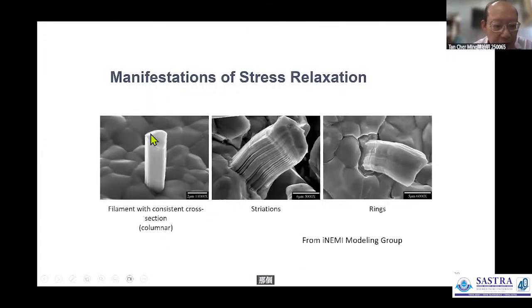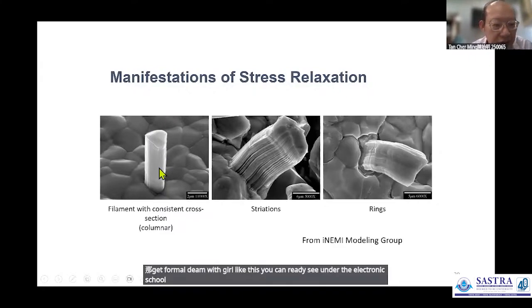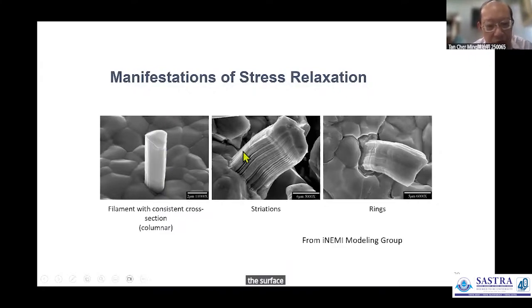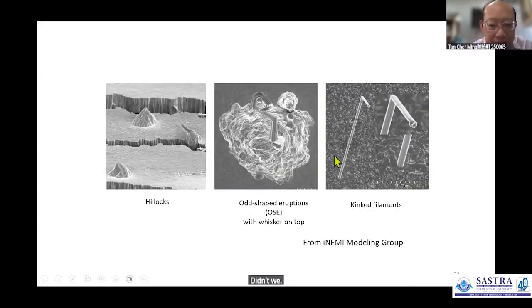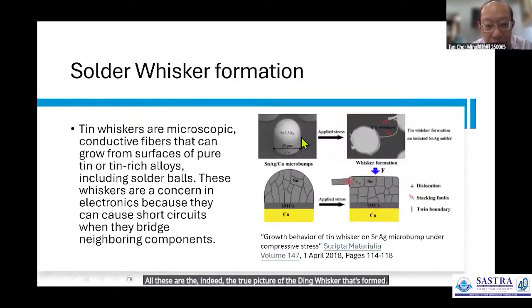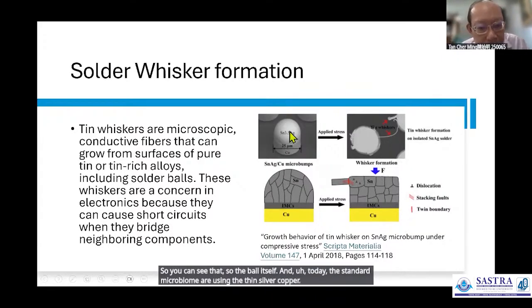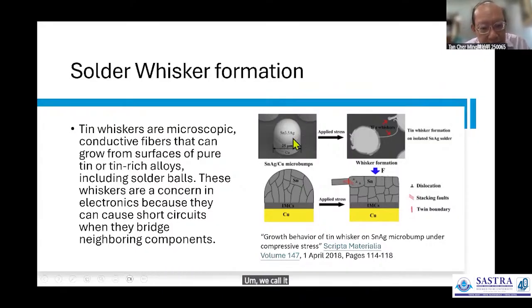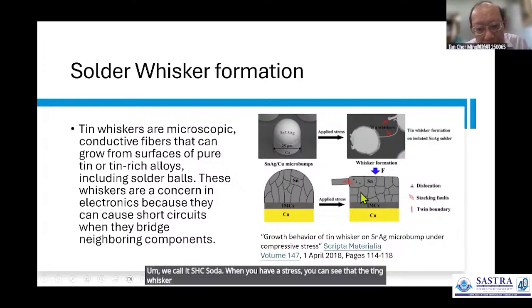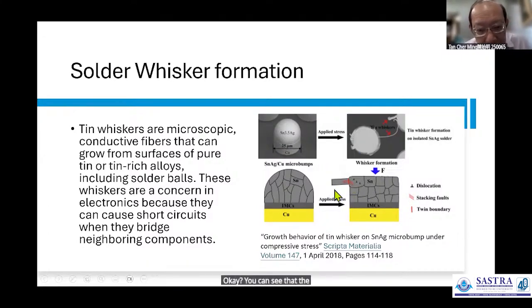Now you can form a tin whisker like this. You can really see it under the electron microscope that the tin actually pops up from the surface. If it is too long, it may bend itself. All these are indeed the true picture of the tin whisker that's formed. So you can see the solder ball itself, and today's standard microbump are using the tin silver copper, we call the SAC solder. When you have a stress, you can see that the tin whisker coming up. Okay, you can see that the tin whisker is coming up from here.